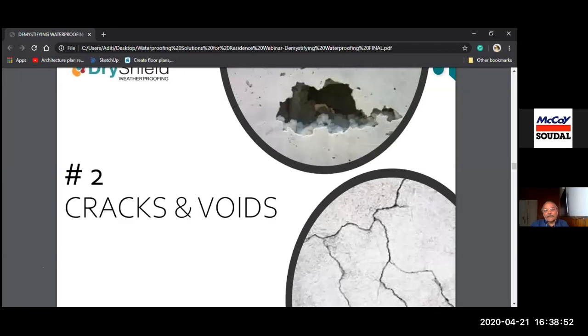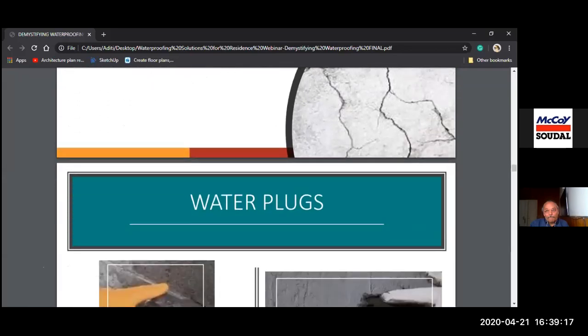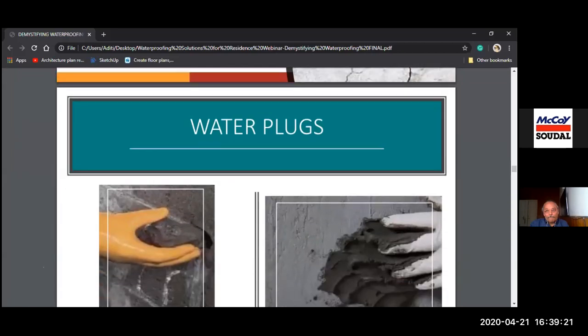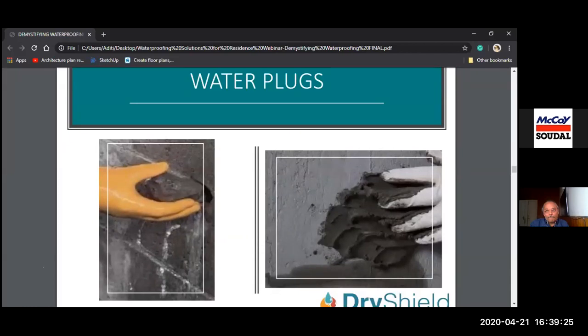The next stage after improvement of your concrete is taking care of these cracks and voids, repairing them. So primarily this is a repair job. This could have been avoided if a good admixture had been used in the beginning, so you wouldn't have got cracks and voids. But now that the cracks and voids have come, it's better to take care of them at this stage only. Water plugs are used when there is active water coming into the basement from cracks or voids. Nothing can stop that water immediately except a good crystalline water plug. Water plugs almost instantaneously stop the water seepage, flowing water.